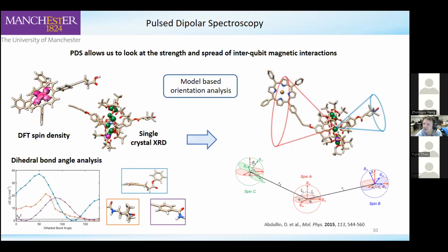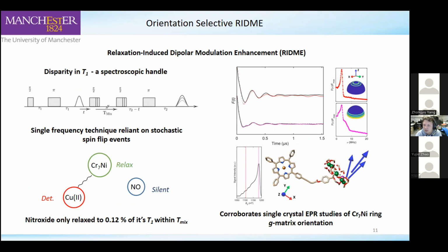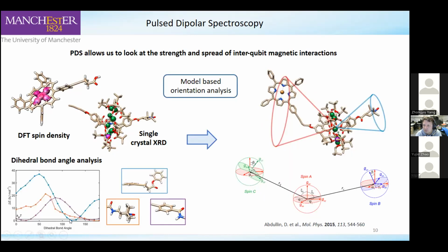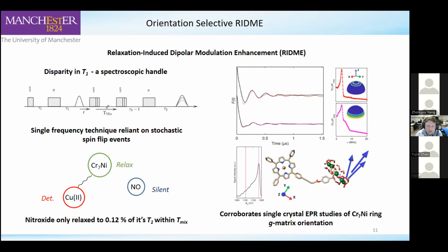Yeah, so that's why we built this model originally, because we were a bit worried that if you had massive flexibility then that interqubit interaction isn't very well defined. But from the dipolar data coupled with this dihedral bond angle analysis that we did, at the freezing point of the solvent the range the bond angle can move around is really quite small, and you get a rigid structure at the temperatures at which we do the experiments. In solution, it could be a different story, but realistically, we're not going to do any of this quantum computing at room temperature just yet.